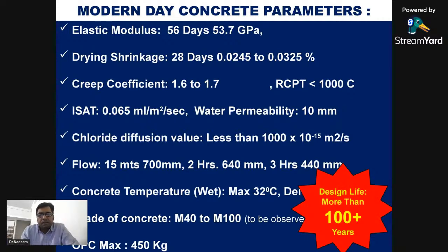These are the typical specifications being mentioned nowadays for all key structures where HPC concrete is being used, where we are looking for a design or service life of more than 100 years. Water permeability less than 10 mm, chloride diffusion less than 1000 into 10 raised to minus 15 meter square per second.